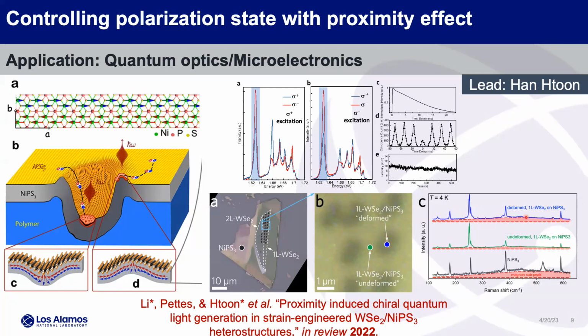The peak is about 450 wave numbers, but it's much higher in the areas where we punch, which would align with the theory that we have, that you have some out of plane magnetic component that's driving the change in chiral state of the tungsten diselenide. So that's why we're picking up always one circular polarization. Whenever we say spin orbit coupling, usually we're talking about circularly polarized light.